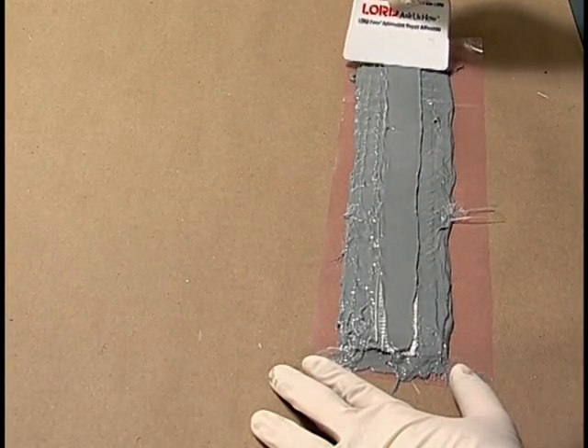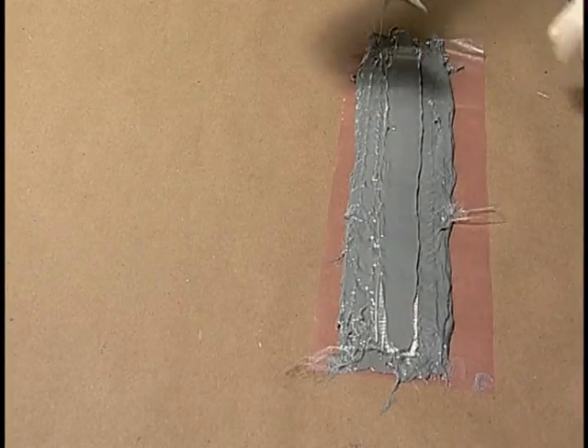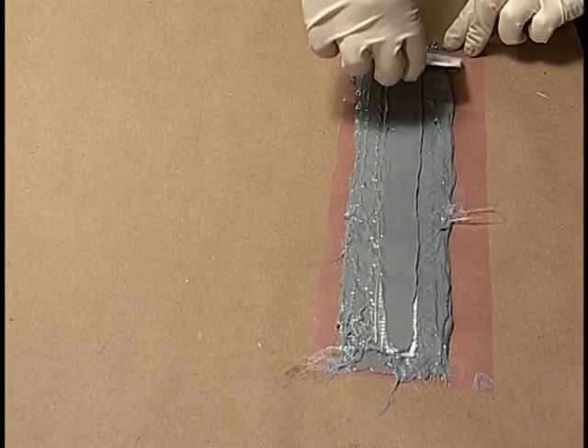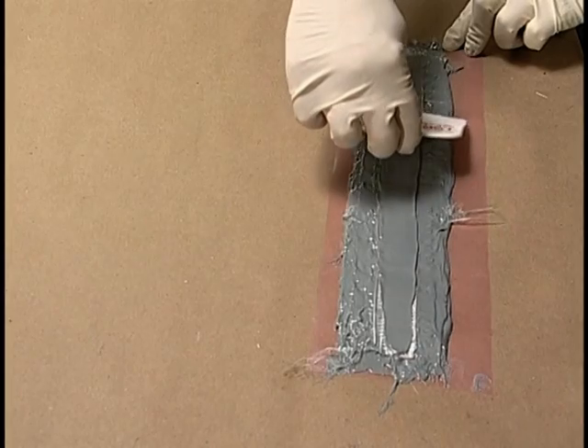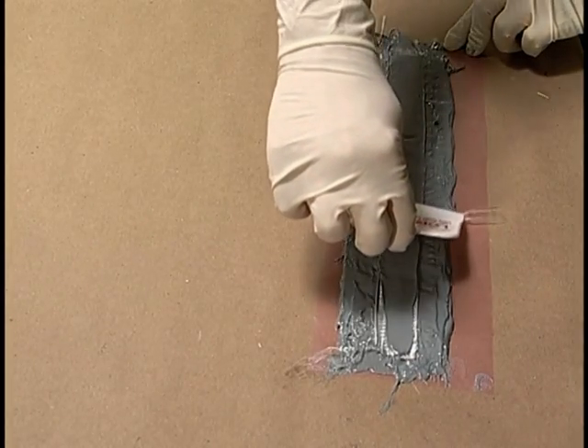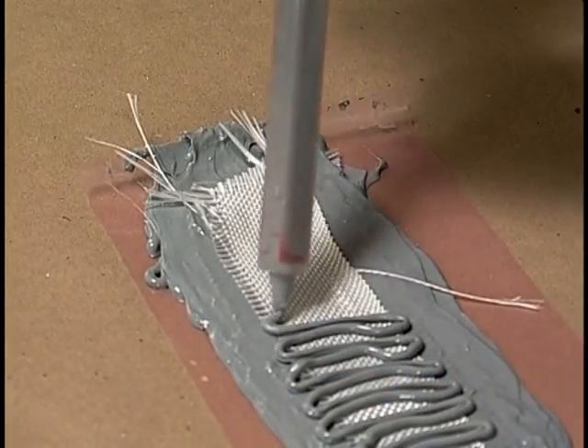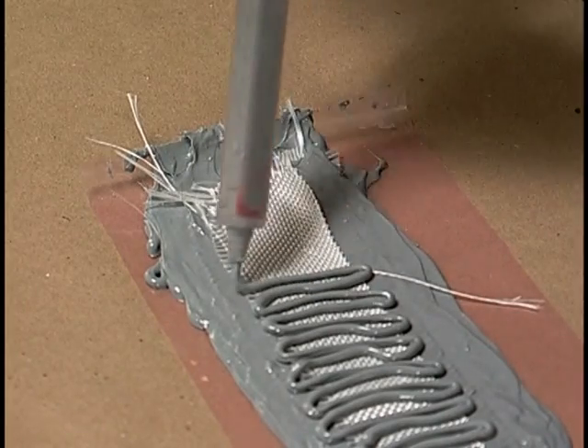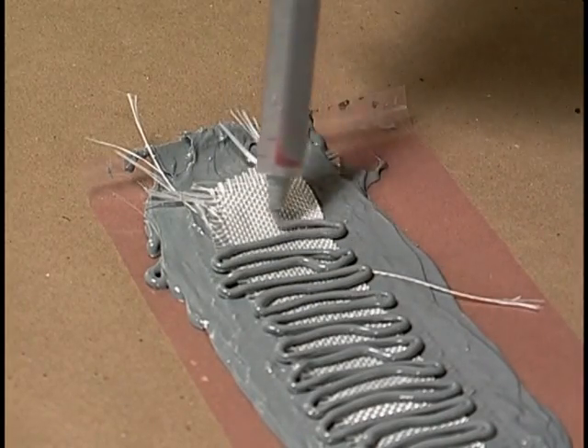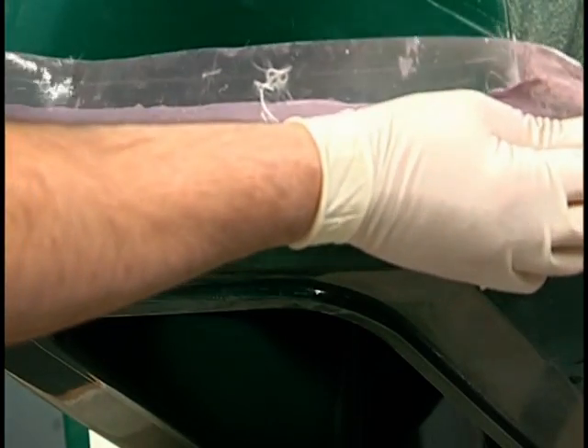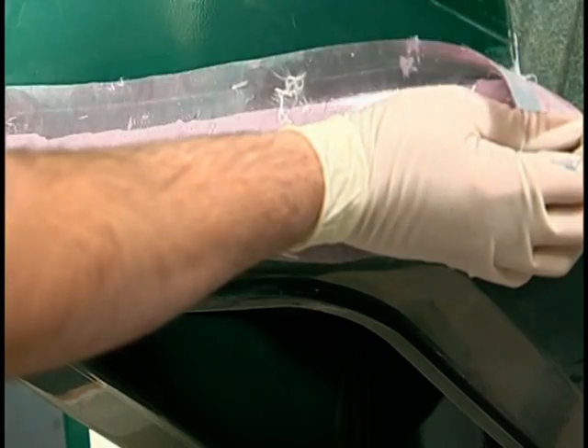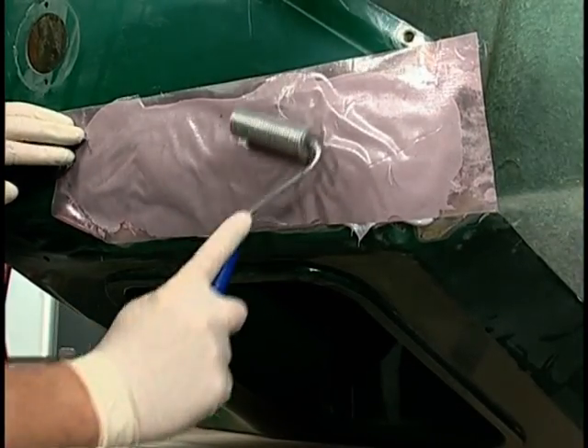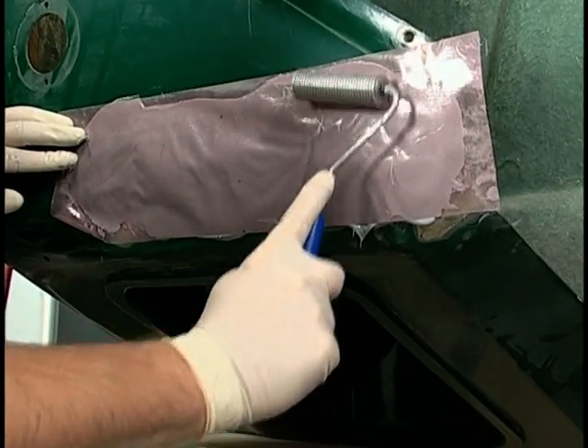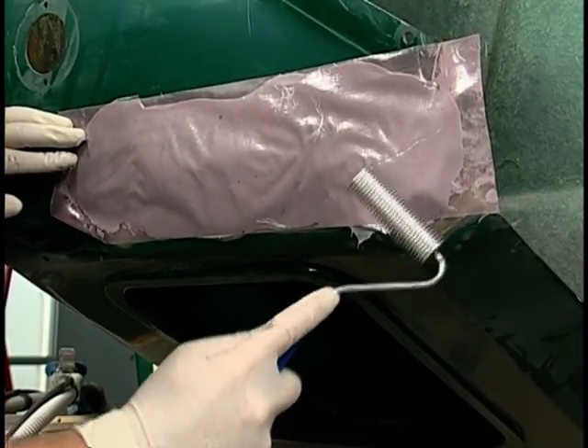It's important to work as much fiberglass cloth into the repair as possible. This controls expansion and contraction in hot and cold temperatures, eliminating read-through or bullseyes. Build 2 to 3 layers, followed by a top coat of adhesive. This patch should now form a pyramid shape. Place the pyramid of fiberglass cloth and adhesive on the prepared area. Work the adhesive into the repair by rolling with the Fusor saturation roller. This eliminates air pockets and pinholes.